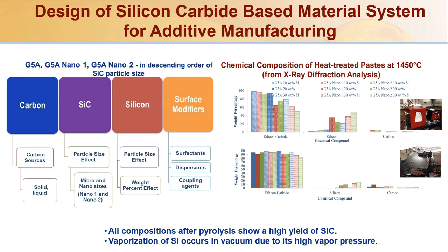So what we found by doing these different developments is all these compositions after the pyrolysis show a very high yield of silicon carbide. If you look on the right side of some of these compositions in the weight percent, you can see a very high amount of silicon carbide, and the amount of carbon is very, very small, which is unreacted carbon, and the silicon in some cases is very, very low as well.